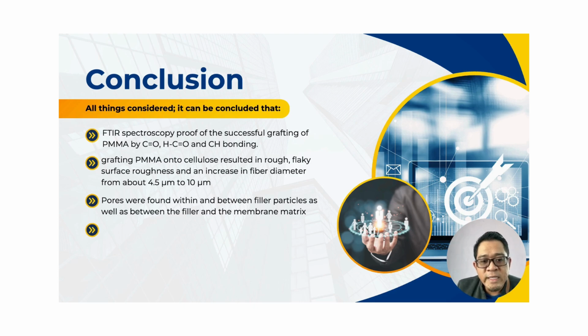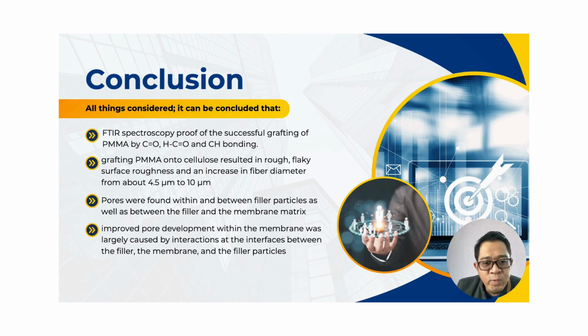Pores were found within and between filler particles as well as between the filler and the membrane. Improved pore development within the membrane was largely caused by interaction at the interface between the filler and the membrane and the filler.